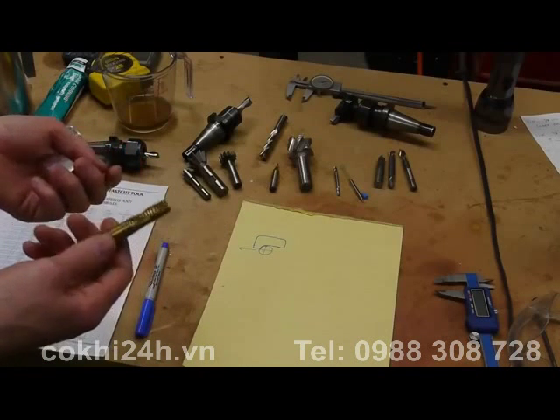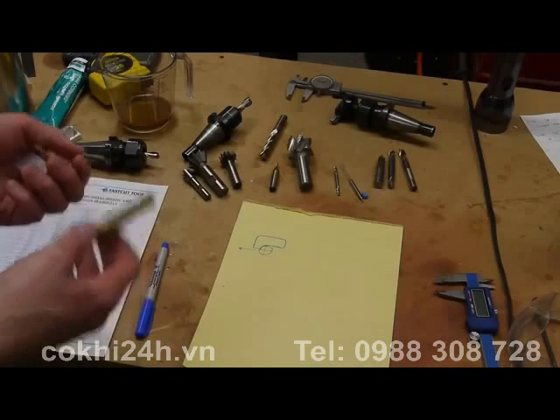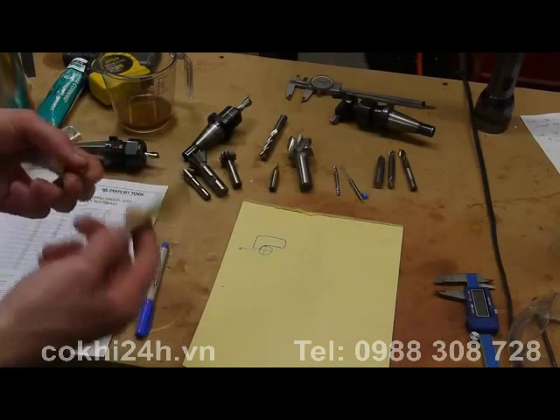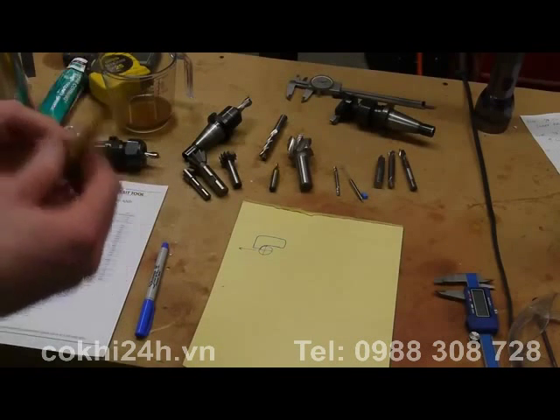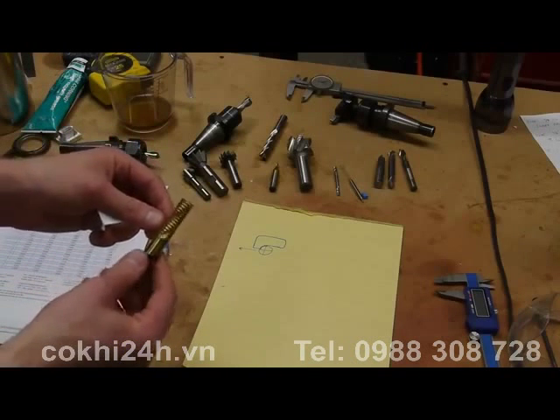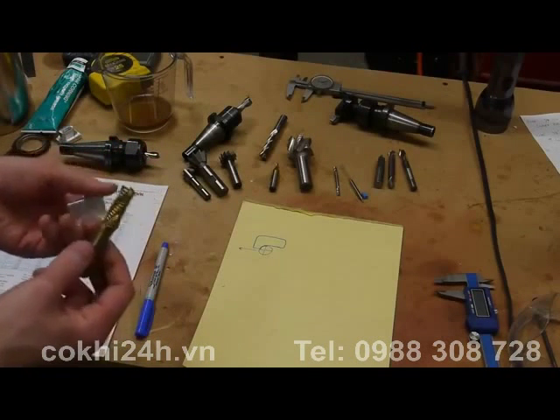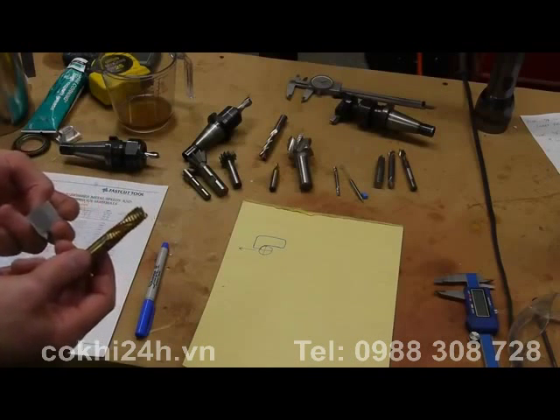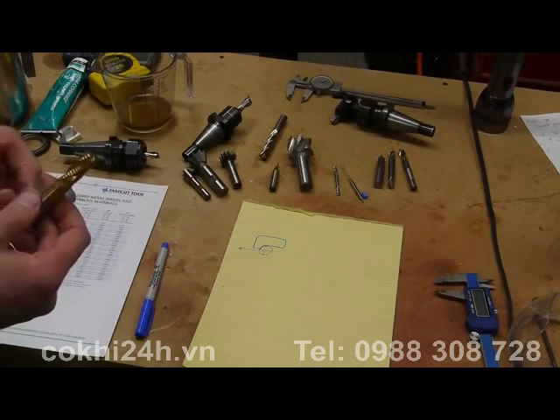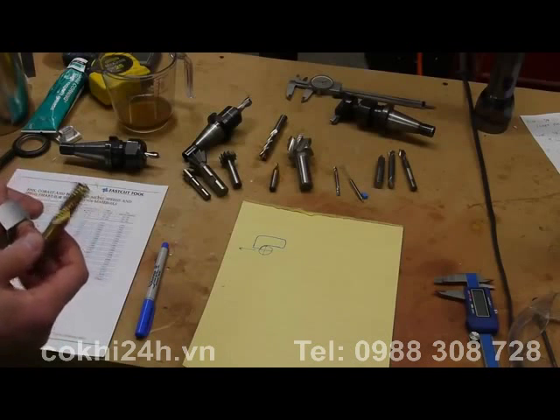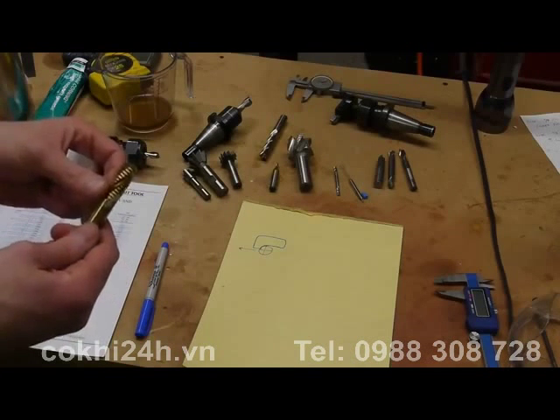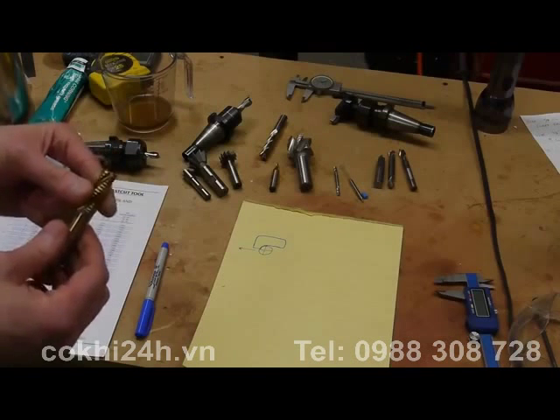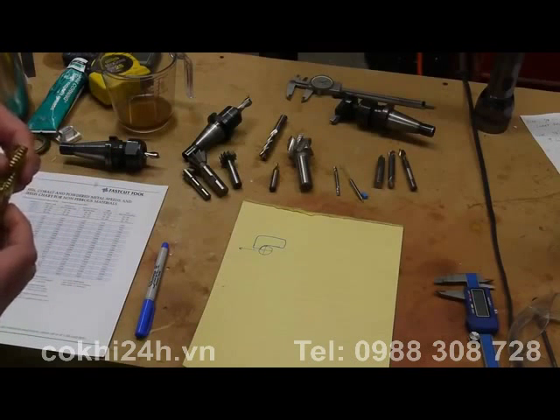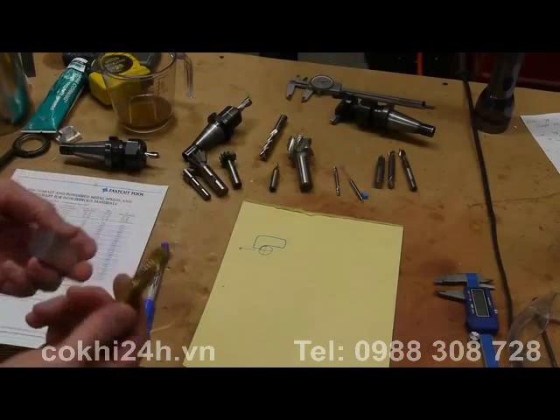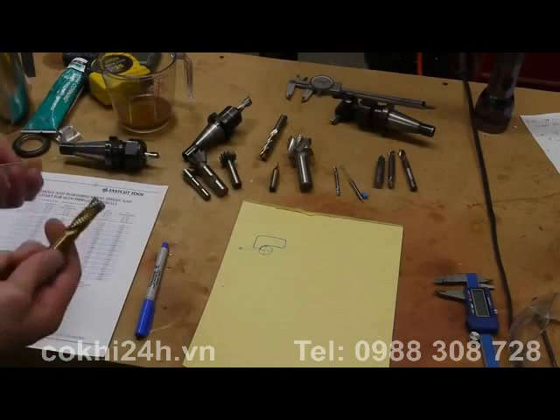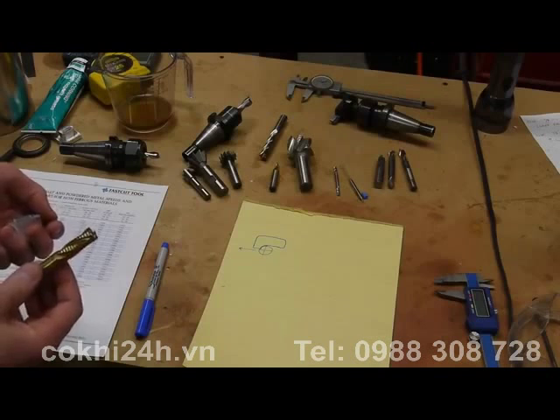Nowadays, there's probably 5 or 6 different common coatings you can get. Titanium carbonitride, titanium aluminum nitride, aluminum titanium nitride, I don't know. There are tons and tons of coatings, but for cutting aluminum and plastics, you generally do not want a coating. I think zirconium nitride is considered okay for aluminum, but you generally just want a really sharp tool for soft things like aluminum and plastic. So if that's mostly what you're going to be milling, high-speed steel uncoated is perfectly fine. As you can see, most of my tooling is just high-speed steel uncoated.